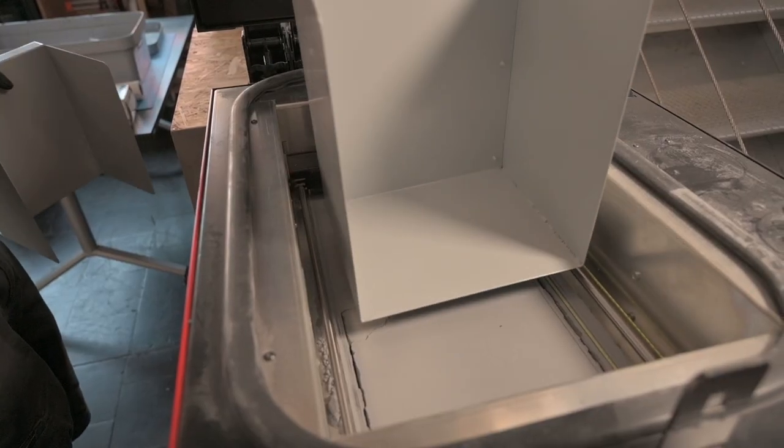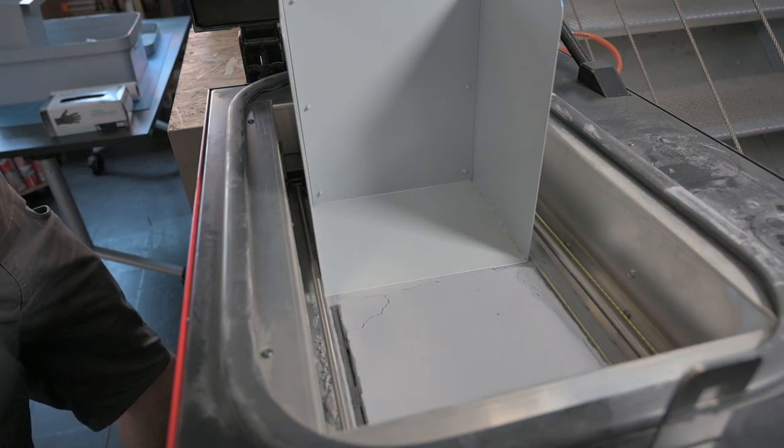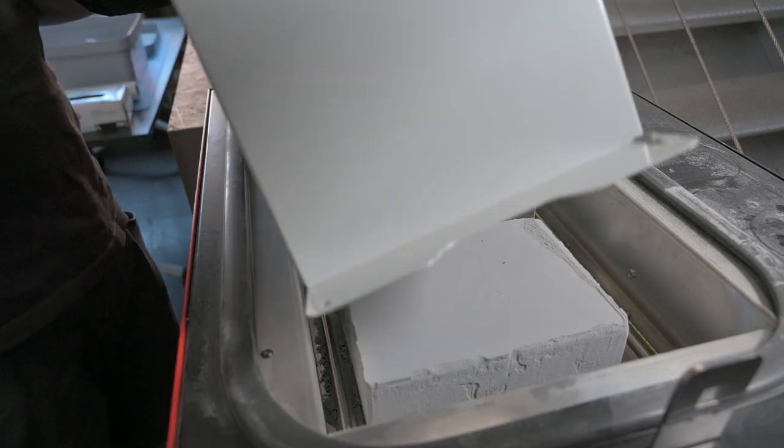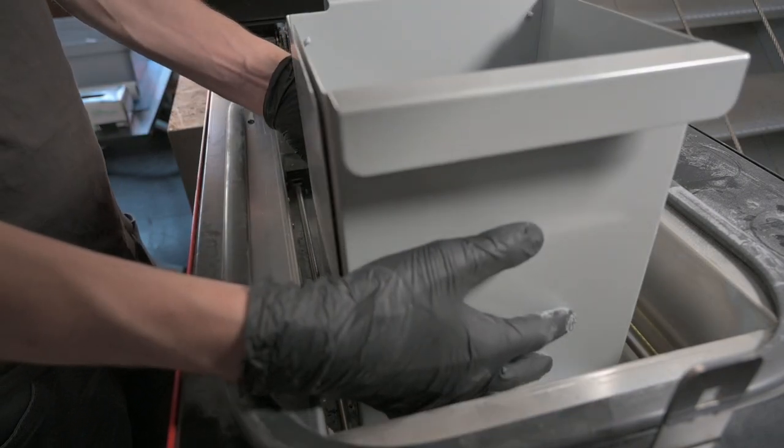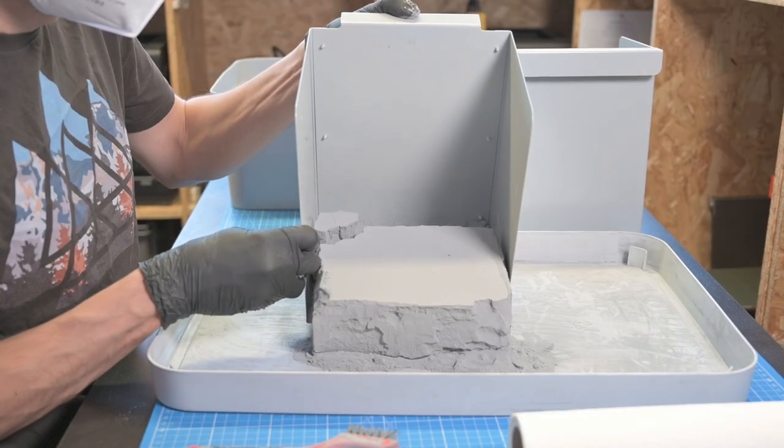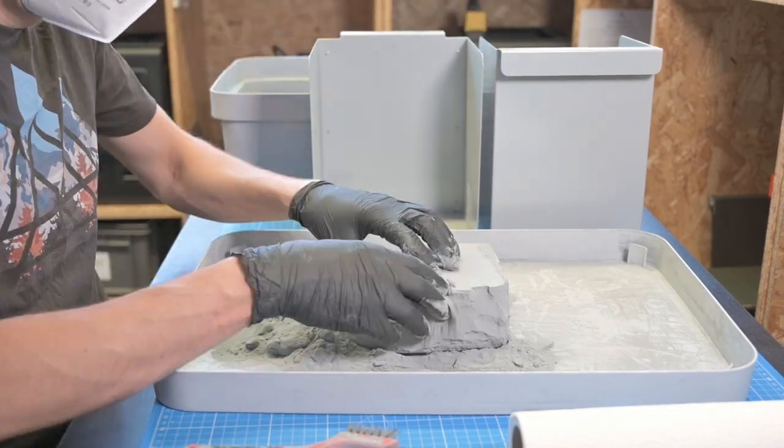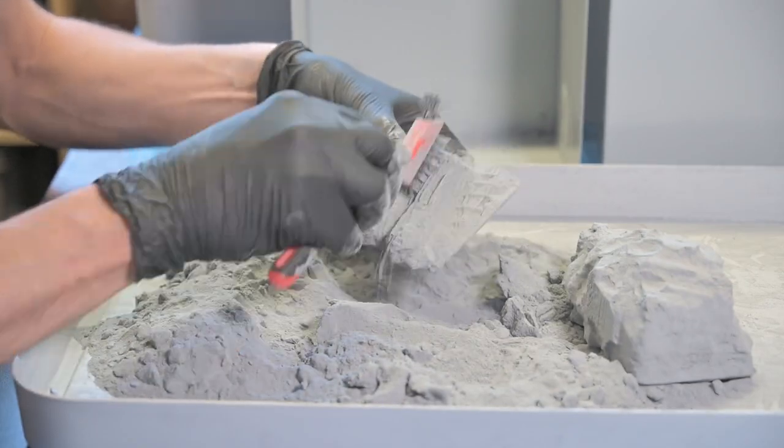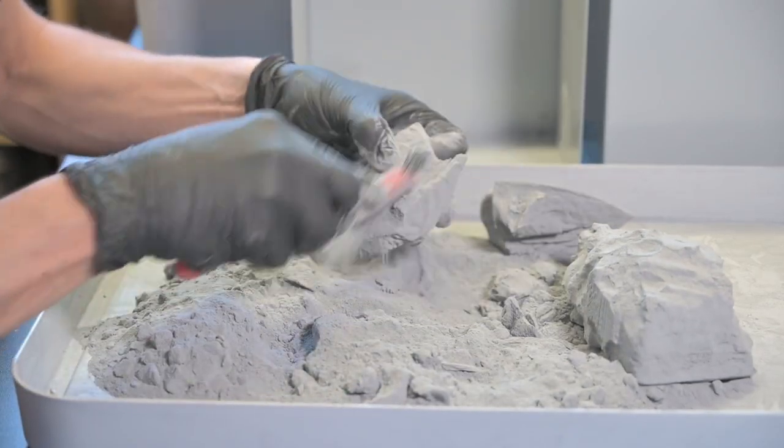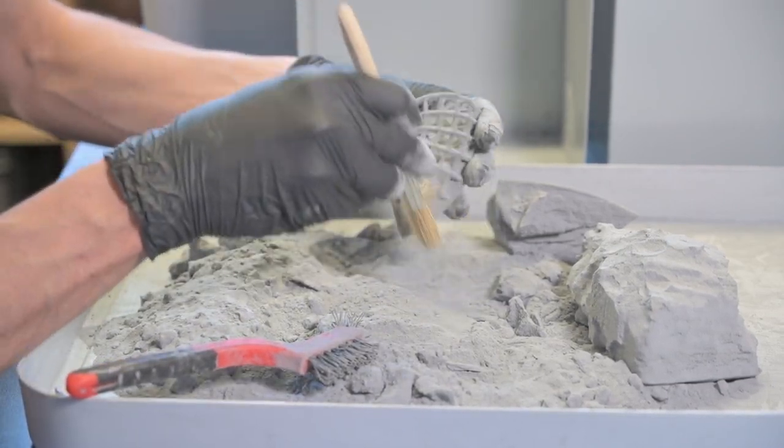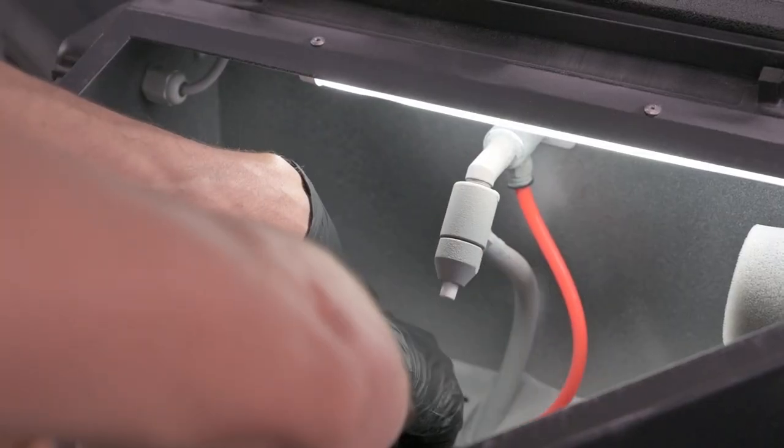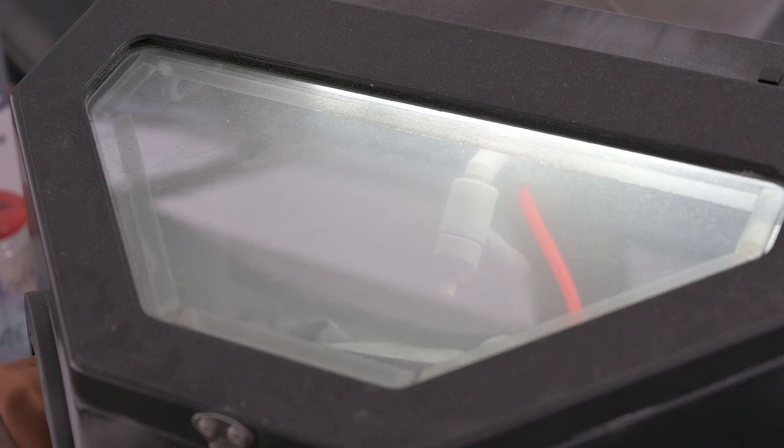Once the printing process is completed, we can remove all the powder and then separate the melted from the loose powder. Once coarse powder residues are removed with gloves and brushes, we can place the printed parts in a chamber where they are sandblasted with fine glass beads.